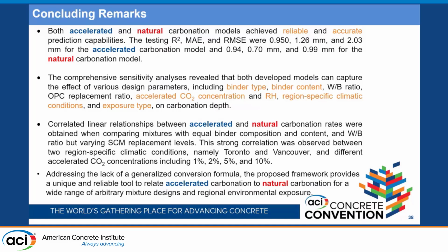Of course, the model has some limitations. For example, how we could input the reactivity of different SCMs. As I told here, we use a reactivity modulus. We could use the straight chemical compositions in the model as input features, but we don't have that much information about the reactivity of the SCMs in the published literature, which is a limitation in terms of data that we have right now. And at the end, this model can be used for different purposes, for durability and for service life modeling based on, for example, the fib codes, or it can be used to quantify the carbon uptake of concrete with different SCM contents.